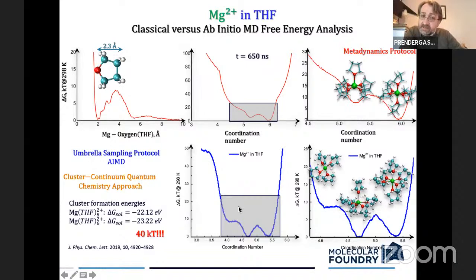When we repeated this analysis with ab initio MD, we saw the picture was even more complicated. We found almost 3 local minima. And surprisingly, the 5-fold coordination and 6-fold coordination, the scale here is not an exact match to the integer number of molecules, but you get the idea when you look at these pictures, they are equivalent in free energy.